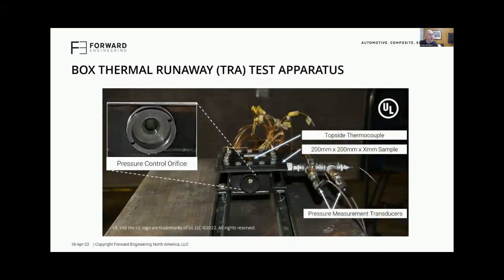So here's a close-up of that orifice. You can see the cutaway in the upper left of that image, showing you the focus on the pressure control orifice. You can see the lithium ion cell, that 18650 cell in the background. In the image to the right there, you can see some wire, which is used to contain or hold those cells as we're dropping them in, and you'll see that in another image. The items over to the right there are, I think I can use my cursor. So here we have pressure transducers, thermocouple, and we're measuring pressure and temperature inside the enclosure, temperature on top of the sample, and that's some close up there.